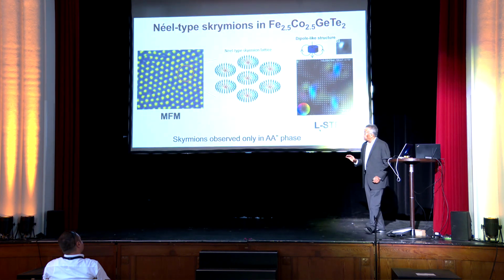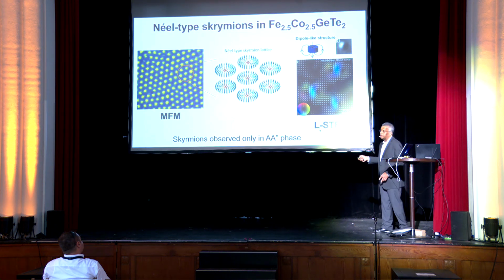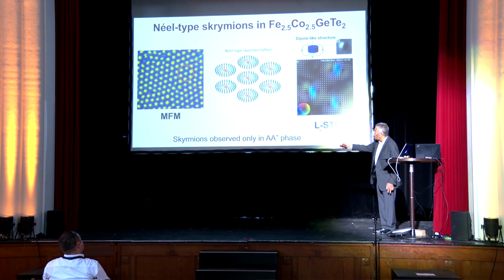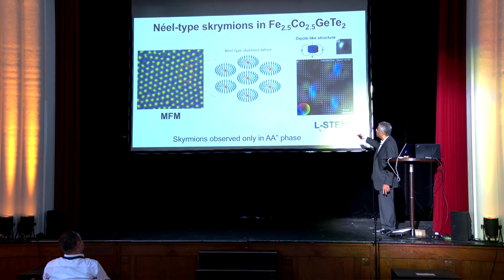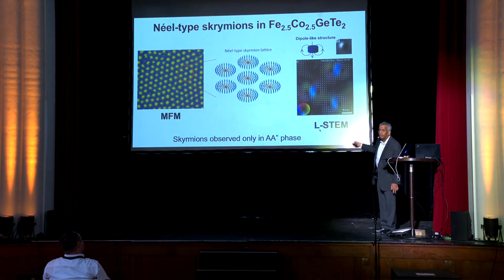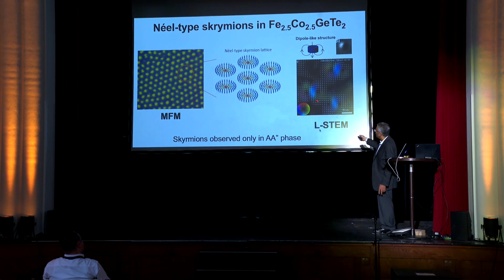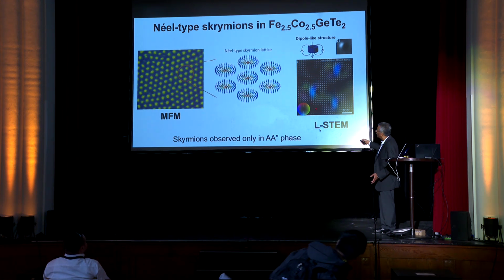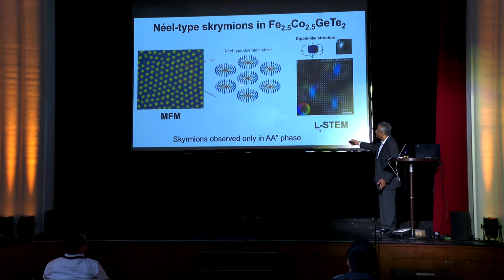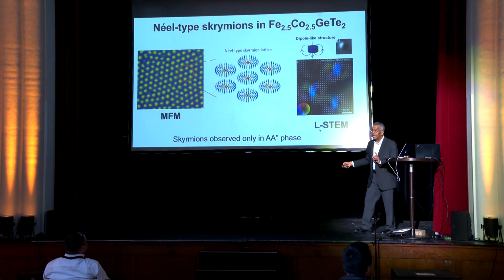Now, at the 50% composition, you start to see the formation of Néel-type skyrmions. These are MFM images. You can capture exactly the same with Lorentz STEM images as well. These are the STEM images. These are the reconstruction of the B field of the skyrmion, and the actual schematic is shown like so. These are Néel-type skyrmions, only in the AA phase.